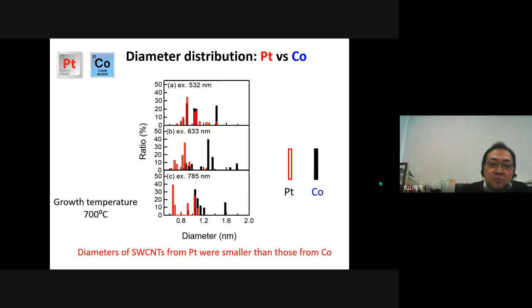These show comparison of nanotube diameter distribution between platinum and cobalt catalysts. The diameter distributions were estimated by RBM peaks in the Raman spectra, measured with 3 excitation wavelengths. Irrespective of the excitation wavelengths, the nanotube diameters from platinum catalysts were smaller than those from cobalt catalysts. So we confirm that the nanotube diameters from platinum catalysts were smaller than those from cobalt catalysts. Next slide, please.